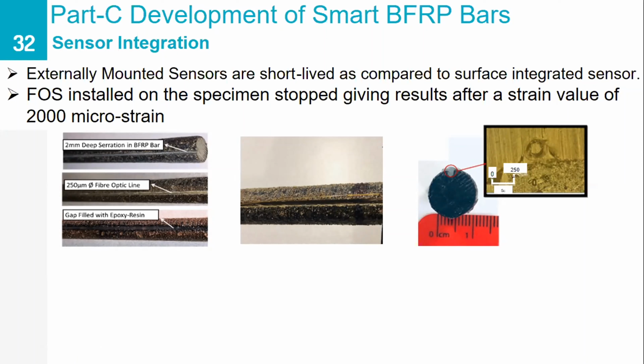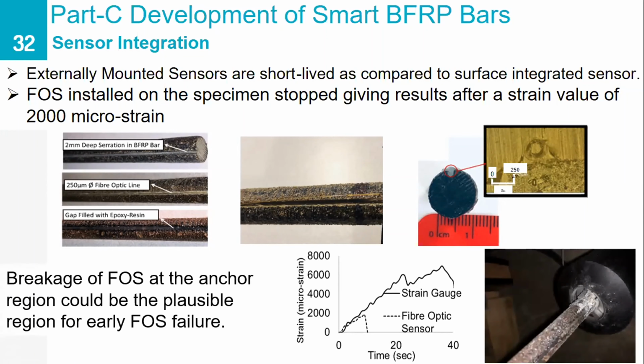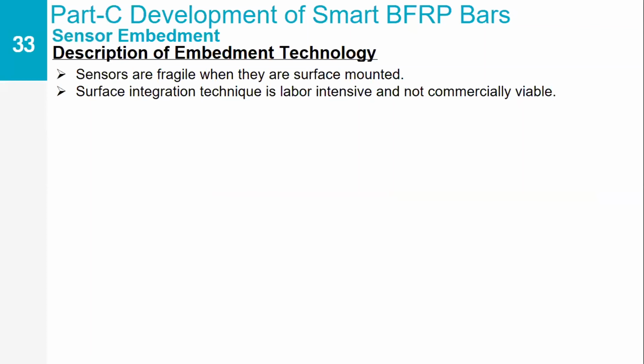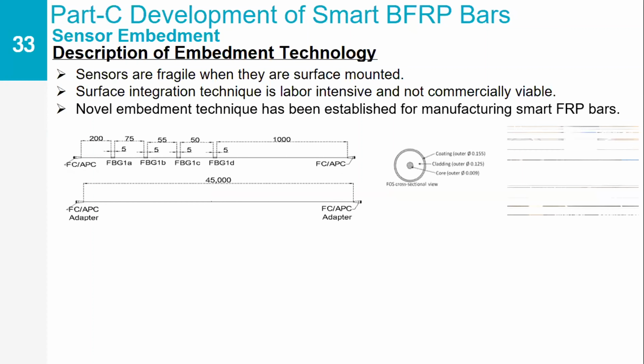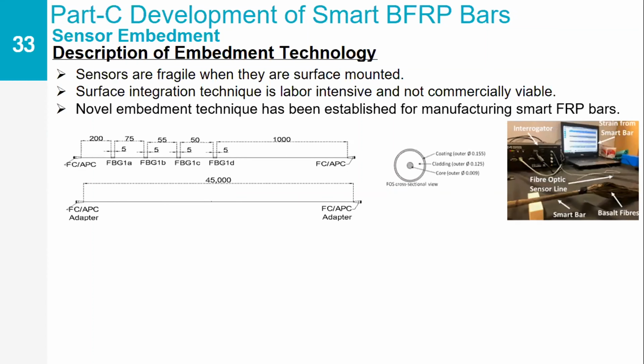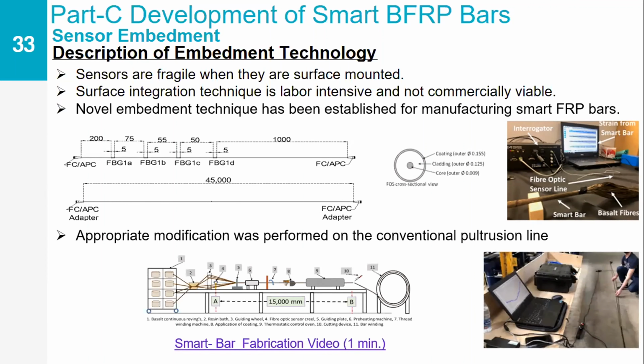It can measure the strains only up to 2000 microstrains because of the breakage of these fiber optic sensors, maybe at the anchor region. Hence, to avoid this, we have come up with a technique to embed the sensors inside the FRP bars. So what has been done is the normal pultrusion line has been modified to install a fibre optic sensor creel, which basically combines with the BFRP fibers before it goes into the resin and the temperature chamber.